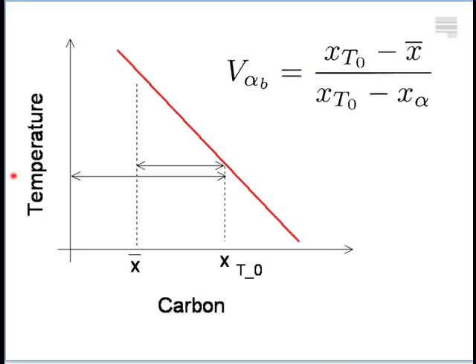Just like we have a phase diagram, I'm plotting temperature versus the carbon concentration. And this is the T0 curve, which defines the concentration of carbon in the austenite where the reaction to bainite must stop, okay? So I can calculate the volume fraction of bainite that I can form by taking this distance and dividing it by this distance, where here is the average carbon concentration of the steel, and this is calculated thermodynamically, and this gives me the volume fraction of bainitic ferrite. I cannot do anything to exceed this volume fraction.